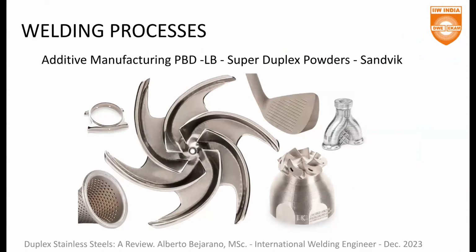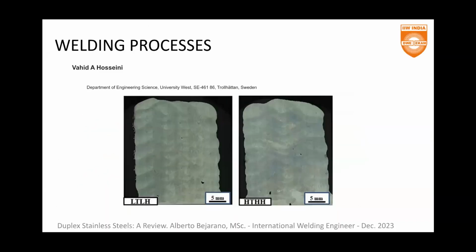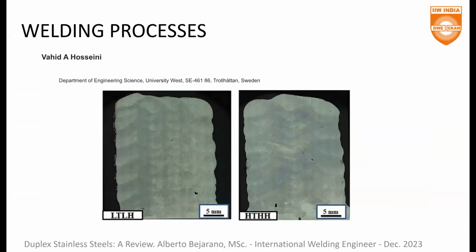So here we have some examples of this kind of products which are susceptible to be printed in duplex stainless steel and super duplex stainless steel. This is powder bed fusion, which is very fine in the appearance of the product, and here we have welding processes. I mean, this is direct energy deposition, which is to weld layers and layers and layers of welding in order to obtain a base volume, which normally has to be machined by a traditional process in a CNC lathe or something like that.